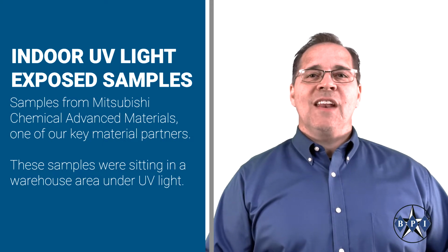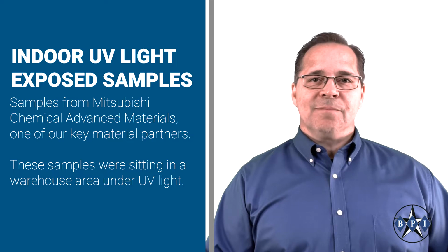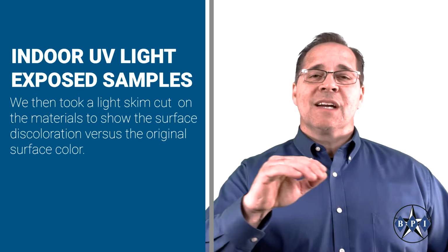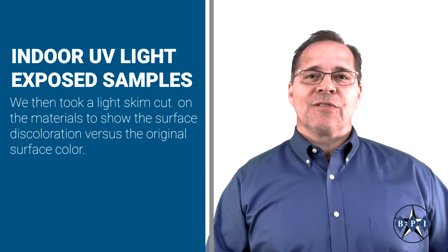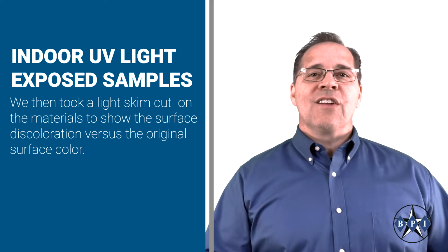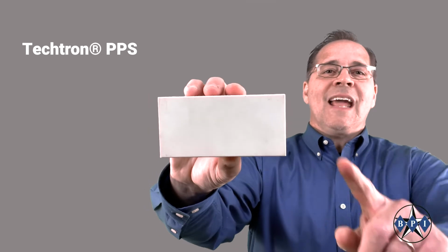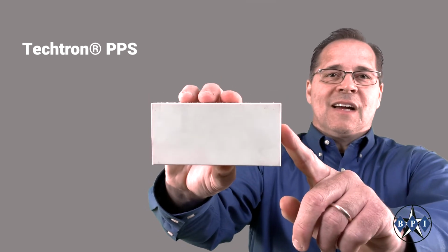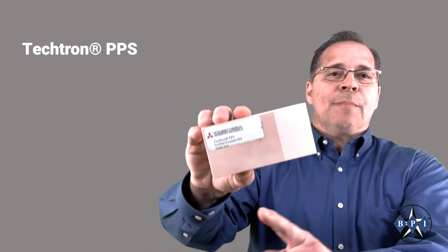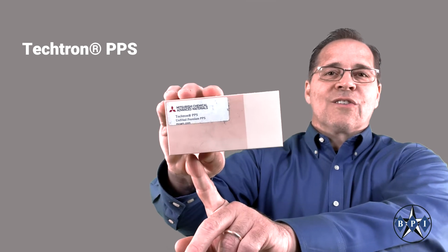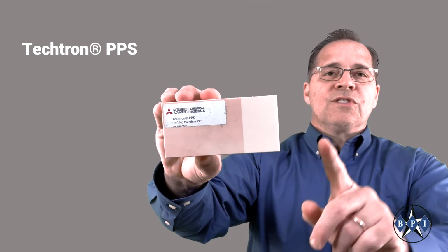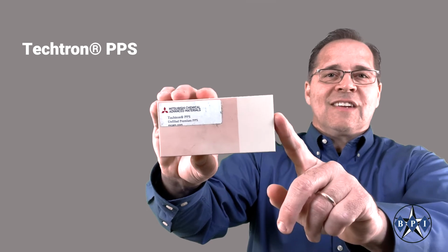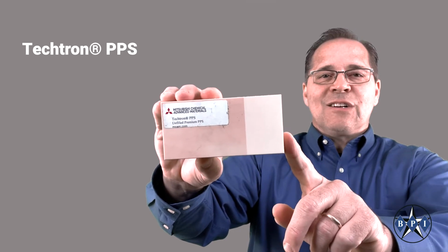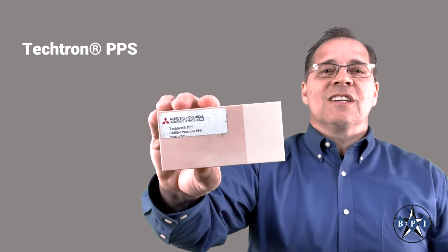These samples were sitting in a warehouse area under UV light. We then took a light skim cut on the materials to show the surface discoloration versus the original surface color. This is Techtron PPS, which normally has a nice light tan cream color. The side that was sitting up exposed to the lighting discolored over time. When we remove just a few thousandths of material off the skin, you see that the material is still fine underneath and the discoloration is only on the surface.